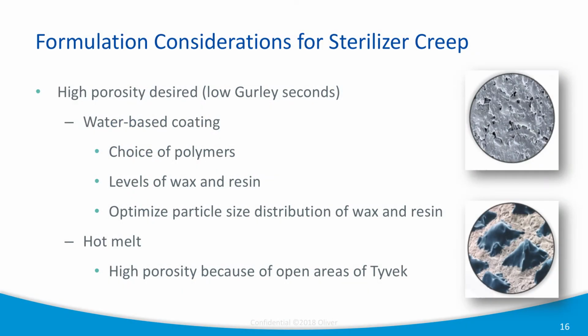On the hot melt side, it's a little different because, as you can see in the picture on the bottom right, we're basically printing islands of hot melt, and there's open areas there. In between the pyramids, that's raw Tyvek. So the gas, the EO gas, can get through. That's a natural advantage of hot melt, that there are fully open areas of Tyvek, and so you naturally have this good porosity that you need for sterilizer creep.